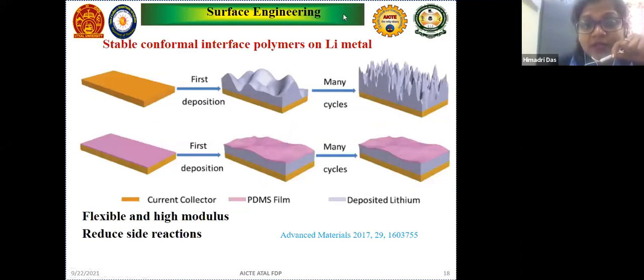Here is one of the approaches, as I mentioned, surface engineering. With surface engineering, we can make an artificial solid electrolyte interface. We can also coat the material with some polymer. If there is no polymer coating, we can see here the dendrite formation has happened after many cycles of charge discharge. When we give a polymer coating, the deposition will not allow the lithium to grow, and the dendrite formation will be reduced.